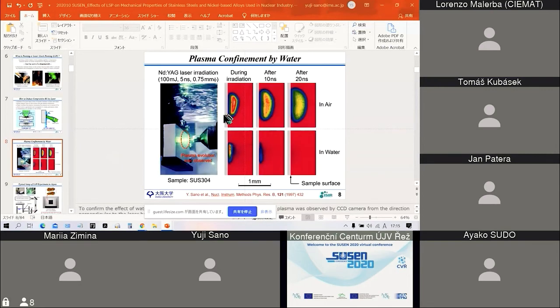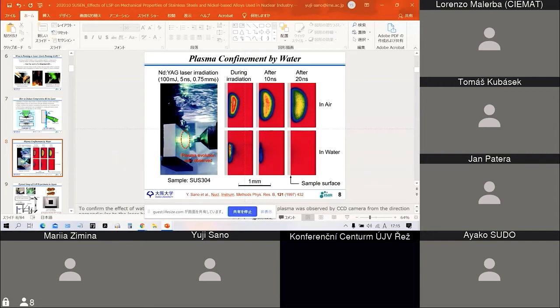This viewgraph shows the effect of water to confine the plasma. In this experiment, we irradiate the laser pulse onto the material underwater. You can see the plasma here. The diameter is about 1 millimeter in this case. This high-pressure plasma expands very rapidly if you irradiate the laser pulse onto the material in air. However, water can confine the plasma like this. Laser energy concentrated in a narrow space increases the plasma pressure significantly, up to several gigapascals.